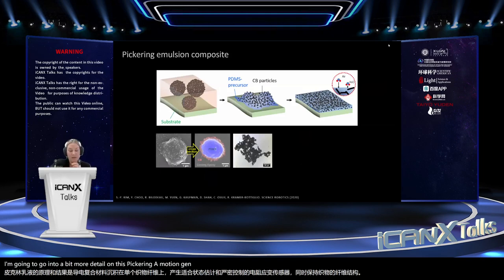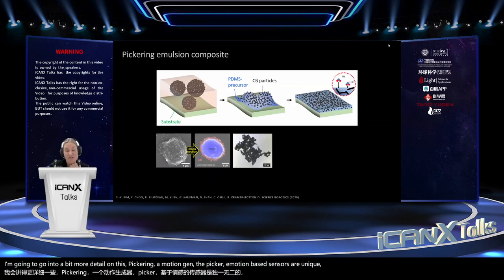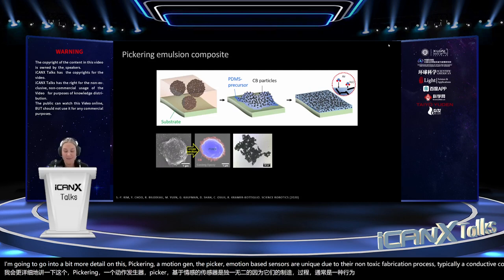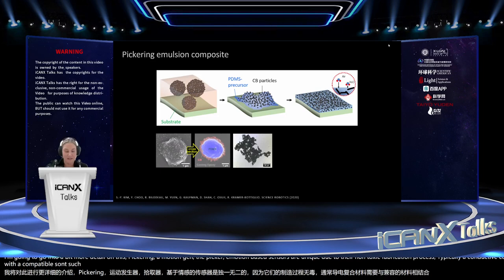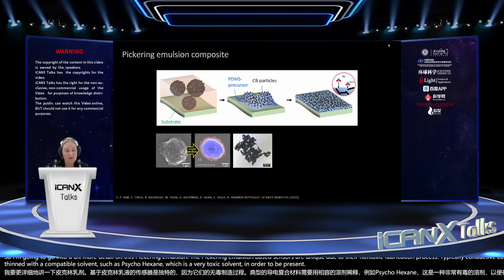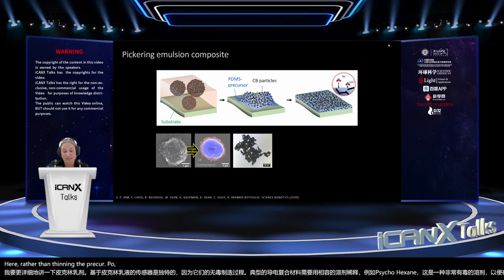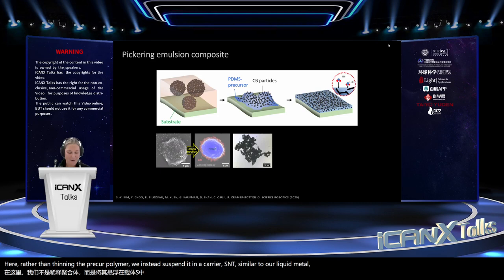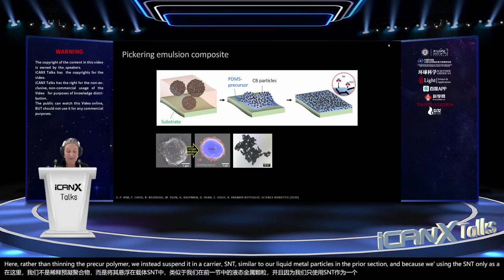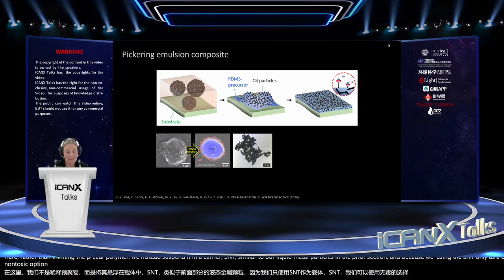The Pickering emulsion-based sensors are unique due to their non-toxic fabrication process. Typically, conductive composites need to be thinned with a compatible solvent, such as cyclohexane, which is a very toxic solvent, in order to be printable. Here, rather than thinning the pre-cure polymer, we instead suspend it in a carrier solvent, similar to our liquid metal particles in the prior section. And because we're using the solvent only as a carrier solvent, we can use a non-toxic option, such as ethanol.